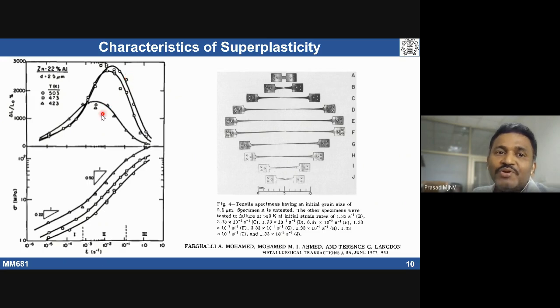we do see the strain rate is shifting towards right, because diffusion activity is going to be more. So you can deform it even at high strain rates and large elongations can be obtained. So within this temperature window, with increasing temperature, the rate of deformation can be improved and large elongation can be obtained when you deform it at higher temperatures.